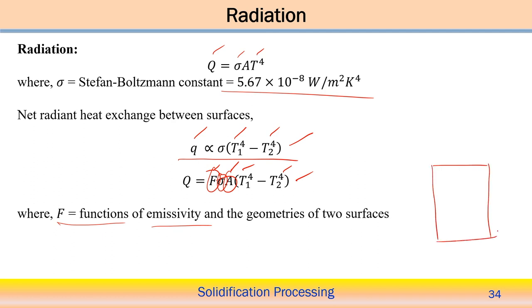Now, once we understand that, from the surface, suppose this is the ladle, so liquid metal is there, and all the sides are usually insulated, so there might not be any heat transfer from all the other surfaces. Whatever heat transfer is there is at the top surface, but in this case both convective and radiative heat transfer occur from the surface. Now, when you try to handle this kind of problem, how do we incorporate both modes of heat transfer, convective and radiative, from the surface? We can combine these two, and we can introduce an effective heat transfer coefficient by taking into account the heat transfer coefficient associated with the radiative heat transfer. That can be done easily, and the problem can be handled in that way.